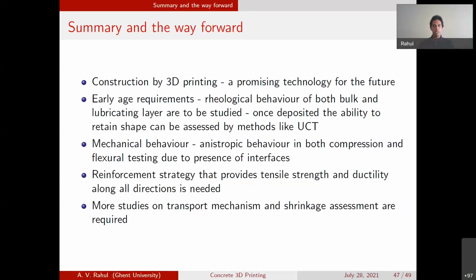The before deposition is essentially the pumping assessment and pumping characterization, where the fact that the lubricating layer is formed at the pipe wall interface has to be taken into account for making a realistic assessment. Once it's pumped out, we need to consider what material parameters are linked with what type of failure, and how these parameters, compressive strength and elastic modulus of fresh concrete, can be characterized.